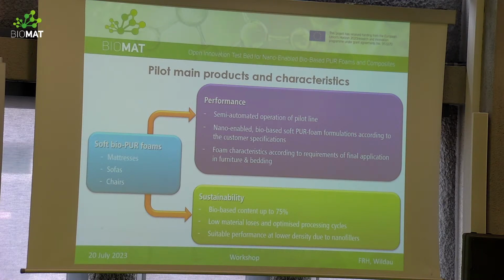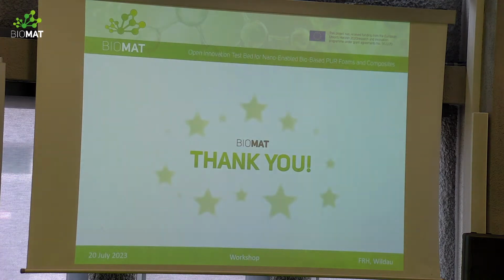Regarding sustainability, we realize at the moment a bio-based content of up to 75 weight%. We don't lose much material, and we can optimize the processing cycles because of the very compact design of the pilot line, and of course the use of sustainable, beneficial nanofillers allows us to develop formulations with required performance but reduced weight. Thank you very much for your attention.